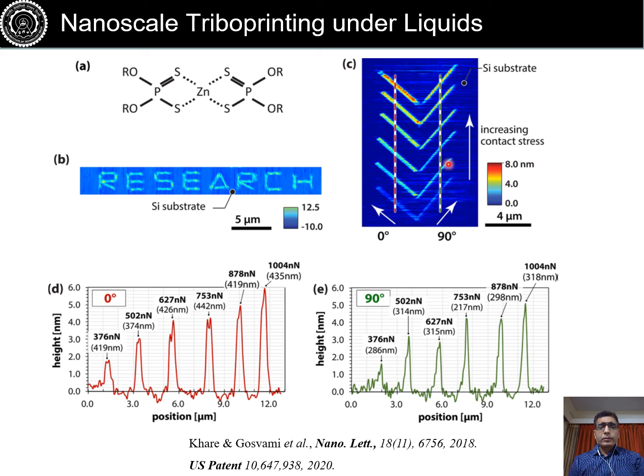In terms of application, there could be several potential applications in future. So we try to understand this patterning and try to see how well we can control this. With ZDDP, we had a lot of experience. We could write these very nice patterns, and we could see that the height of these patterns can be varied by changing the load, which increases the contact stress, and we see that contact stress activates the reaction,